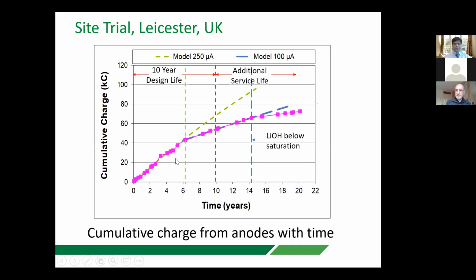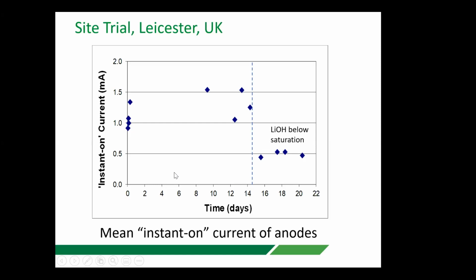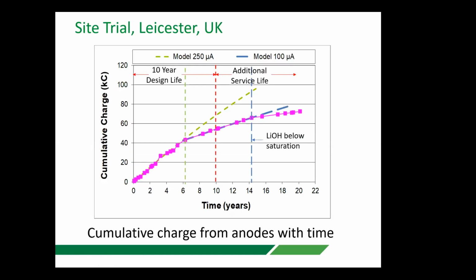Now, when we started analyzing the current output, and we converted it into cumulative charge delivered, as an average of all the anodes, we could see that up to about year 6, the line fitted what we predicted by modeling. So this particular line reflects a model that would start with a current output for each anode of 250 microamps. And the only thing that's reducing the current is the fact that you're reducing the surface area as you're shrinking the zinc anode. But at 6 years, that tended to deviate away from that line into the second line, which fitted a model of more like 100 microamps.